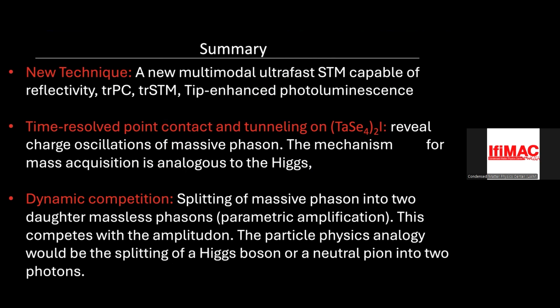So this is the summary. We have this new technique. We can do reflectivity, time-resolved point contact, time-resolved STM, tip-enhanced photoluminescence, all kinds of measurements with one instrument. We can see these charge oscillations, the massive phason, where the mass acquisition mechanism is analogous to the Higgs. And then there's a dynamic competition between the phason and the amplitude on in this system. Thank you for your time.